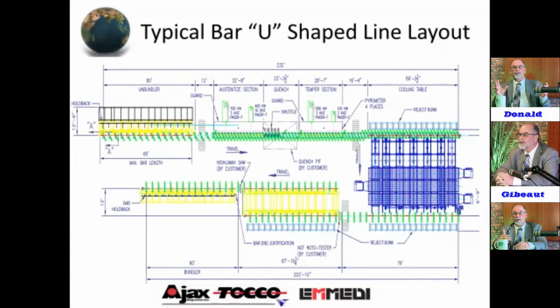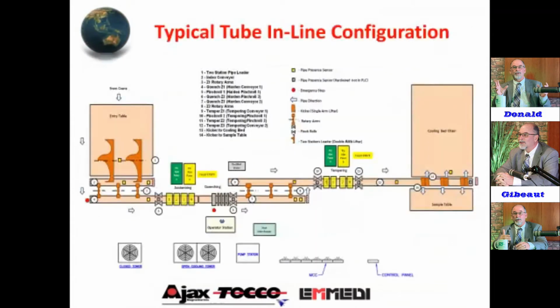Usually there's a water base that's put on an API product after these heat treat lines. And we can control the temperature close enough off that cooling bed that we don't have to reheat it, which is the normal for coating systems. The only time that gets a little squirrely is when you have to stop the line, but you can keep that cooling bed going, and it's a cooling process. It's not a heating process. So you can keep that going and empty that whole cooling bed and run it through at the temperature through that coating system. And it cures out the coating before it gets put out of the system.